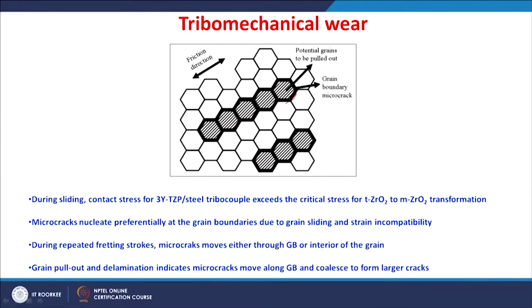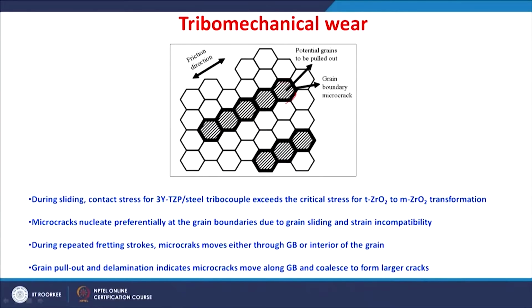So, when there is a transformation from tetragonal to monoclinic, there is a volume expansion and then a microcrack nucleates. The microcracks nucleate preferentially along the grain boundary, mainly because of the grain sliding and the strain incompatibility. So, during continuous fretting, because of the repeated fretting strokes, these microcracks move either through the grain boundary or to the interior of the grain.